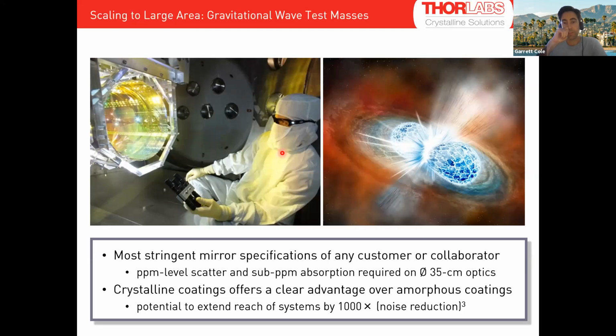This is obviously the most stringent customer, lowest absorption possible, lowest scatter possible, but then even most challenging for us, large area, right? Right now, we can't even go beyond 20 centimeters due to the availability of gallium arsenide seed wafers. And they would like 35 centimeters, which is a major challenge. But we have demonstrated significant improvements in Brownian noise, which means that if you were to run a cryogenic system here, you'd have 10 times lower noise in the interferometer if you were to optimize everything else, to be clear.